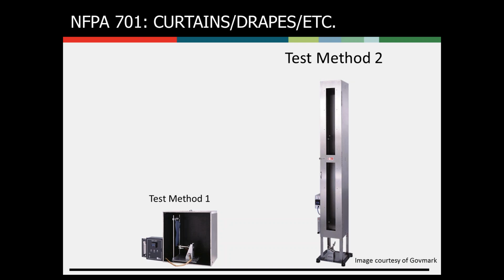It's ignited at the bottom by a 3/8 inch methane burner, and it's positioned there for 2 minutes. And so this test, you can see the time and the requirement put on it, 2 minutes compared to 45 seconds for the previous, is a pretty significant exposure. And so if the specimen continues to burn for 2 seconds after the burner is shut off, then it's a failure. In addition, there's char length measurements that are performed afterwards as well. And so if the char length is too great, basically if the fire has burned up the specimen too far, you will fail the test.